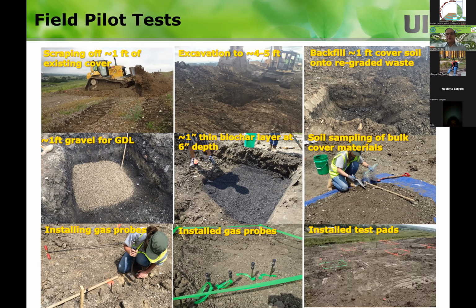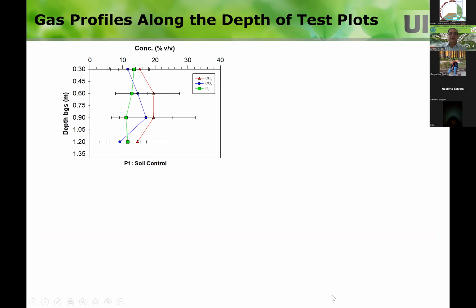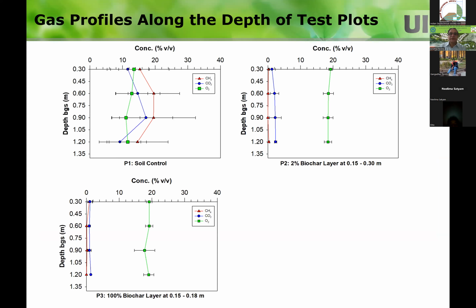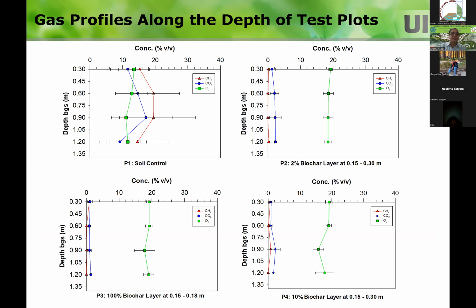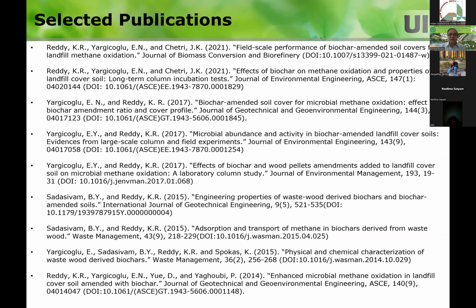And this is how installed test pads look like. So we have a bunch of them, and we have replicates. And the results, I'm just showing the main results. So if you look at just the soil control, you can see the concentrations are higher. But if you have, let's say, 10% biochar, the concentrations are lower. So obviously, even under the field scenario, you can see significant decrease in the methane concentrations and CO2 concentrations. So there are a lot of publications.